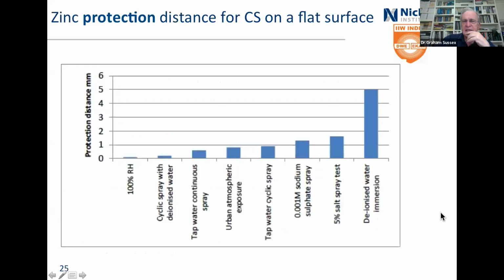Okay, this is to give you an indication of how far apart you have to have things before you can say we don't have to worry about what's going to happen and what the environment is. This is looking at zinc protection across a carbon steel flat surface because it's a relatively easy thing to measure. Surprising how far things will go. So at 100% relative humidity, you get very little protection, very little conductivity through the film that's on the surface. If you're going to spray it with deionized water cyclically, then nothing's going to build up. It's going to wash clean.